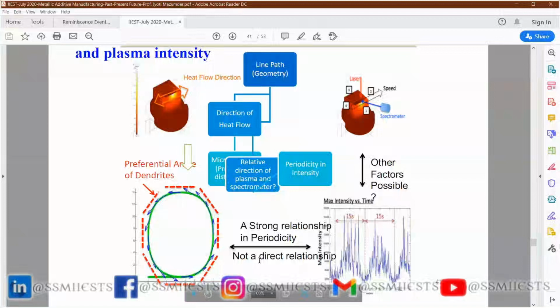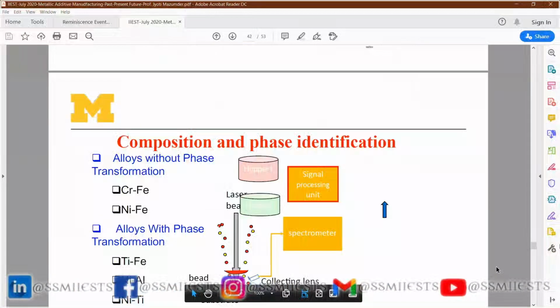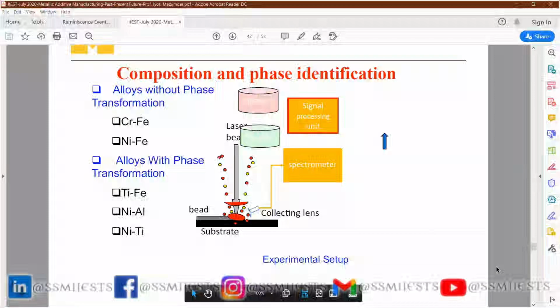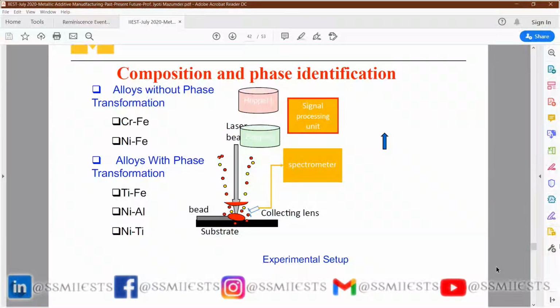For composition and phase identification, what we have done is we collected the light, deposited alloys without phase transformation like chromium iron or nickel iron. They are soluble to a large extent. And also alloys with phase transformation like titanium iron, nickel aluminum, nickel titanium, depositing that, collecting the light, and developing our algorithm for signal processing, we can tell you the composition too.